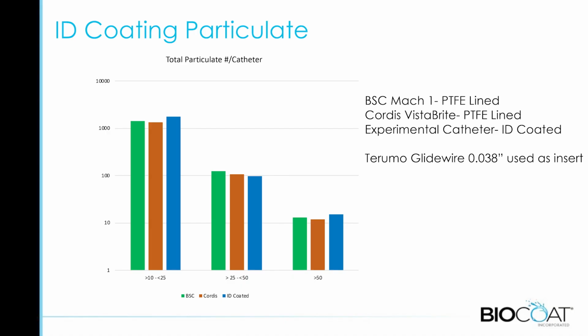Well, that's a really interesting question that we've, as developing this, had really been wondering about, because there's so much focus on particulate generation from coatings. What's interesting is there's not been as much particulate data coming from PTFE itself. And when we compared these two, again, through that same inner lumen coating, we found actually very comparable levels of particulates coming from the Teflon line catheter as well as this hydrophilic coating line catheter, both by the absolute numbers and by the different bin sizes that FDA recommends. So that greater, 10 to 25 micron size, the 25 to 50 micron size, and then the greater than 50 micron size. In all three cases, we are getting very comparable numbers to PTFE.